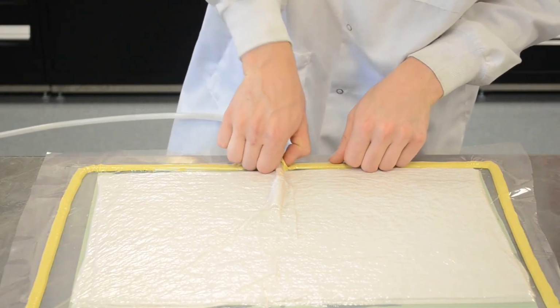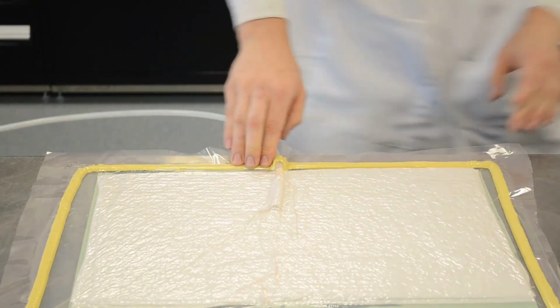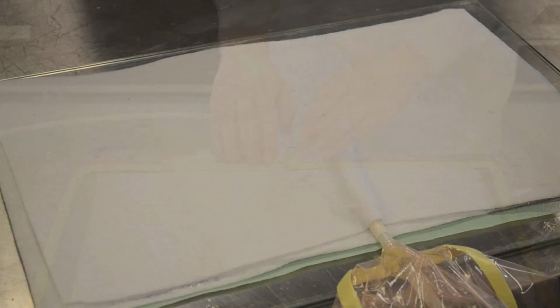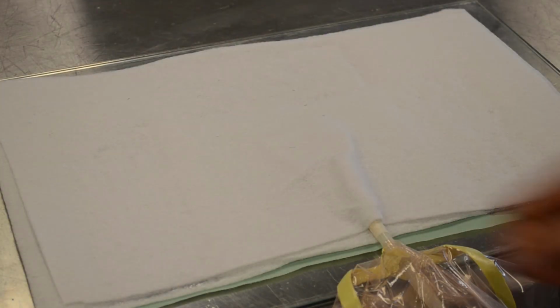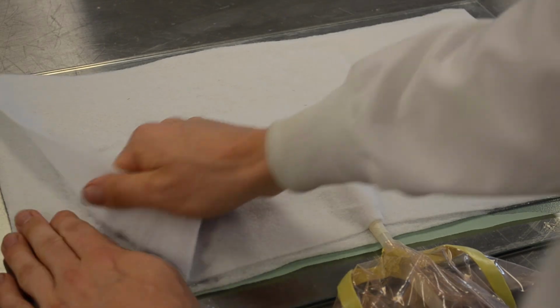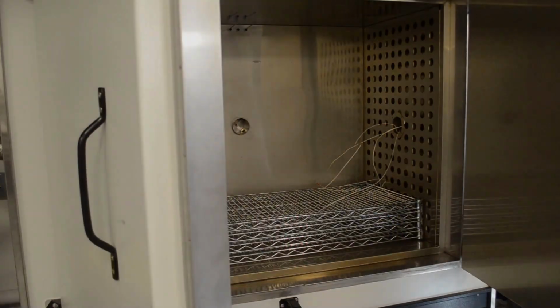After our samples have cured for the recommended time, we can remove them from the tool. The time to demold can usually be decreased by heating to a moderate temperature, however this can slightly increase deformation due to thermal expansion effects and physical aging.